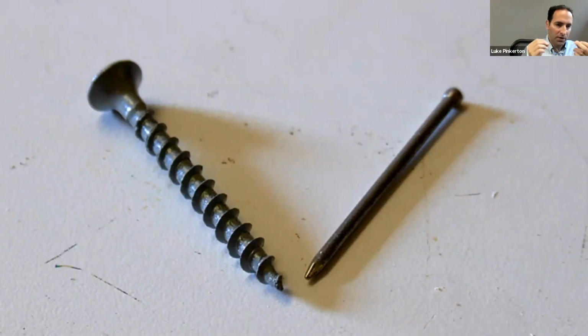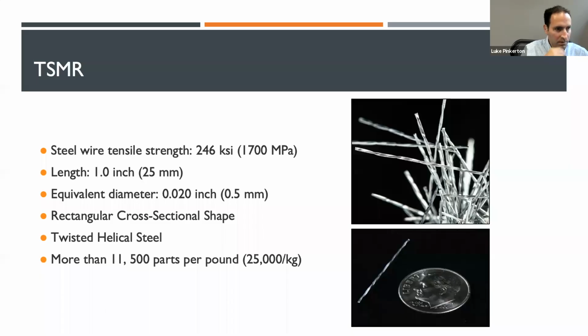So the behavior is driven by the twist and that untwisting failure mechanism versus just friction, which is what governs something that's straight or maybe has a discrete anchorage point like rebar. Or straight is what you would typically see in, say, fiber reinforced concrete products. The product itself is made of high tensile strength steel, similar to what you have in pre-stressing strands. It's about 1 inch long, 0.5 millimeter diameter. It's actually shaped like a rectangle and then twisted about its own axis. And it's relatively small. So there's about 11,500 parts per pound or 25,000 parts per kilogram, which allows us to get quite a bit of performance and efficiency and consistency, even when it's applied at relatively low dosage. And dosage means the amount of pounds per cubic yard that you add to the concrete.